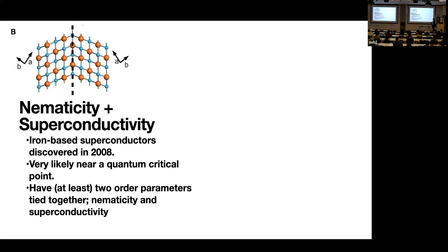And it turns out that there are at least a couple of order parameters that are tied together as a function of temperature, and that's what made the system kind of complicated. One experiment that we did when I was a postdoc with Ian Fisher at Stanford and Junho Chu, who's now a professor in Washington, was that we applied strain on these materials, similar to the strain that I showed you before. We were getting rid of these domain wall boundaries.